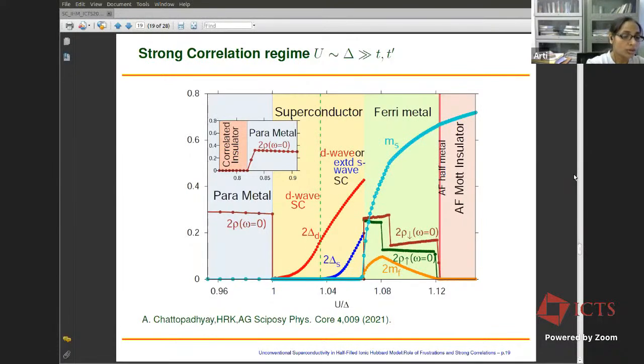As you increase the electron-electron interaction, the first thing that happens is that the gap in the charge density wave insulator gets closed and the system becomes a paramagnetic metal. As you keep increasing the strength of electron-electron interaction further, the D wave superconductivity turns on and it survives as long as the system does not become magnetically ordered. So there is a transition from the D wave superconducting phase to a ferrimagnetic metal, followed by a transition into an antiferromagnetic Mott insulator as we keep increasing the strength of electron-electron interaction.